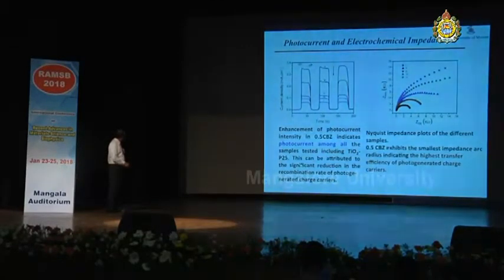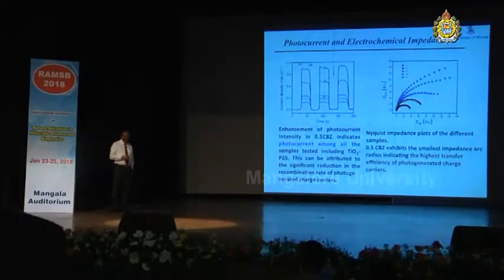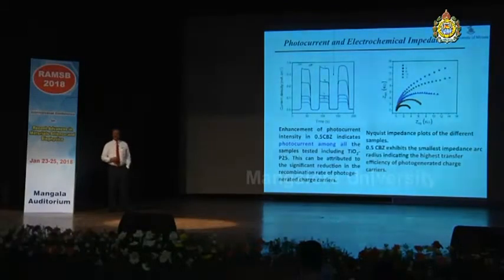And this is attributed to the significant reduction in the recombination rate of generated charge carriers. This I explained earlier, the main drawbacks of zinc oxide or other pure metal oxides. And the presence of the cesium oxide helps significantly in controlling these photo-generated charge carriers. The recombination process can be controlled.